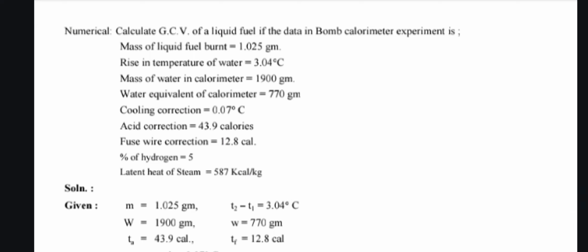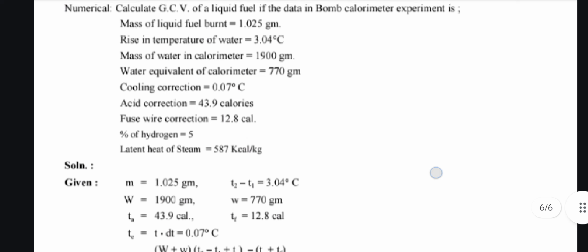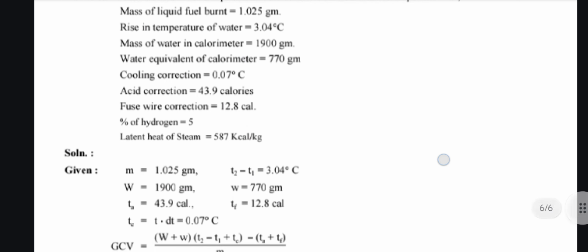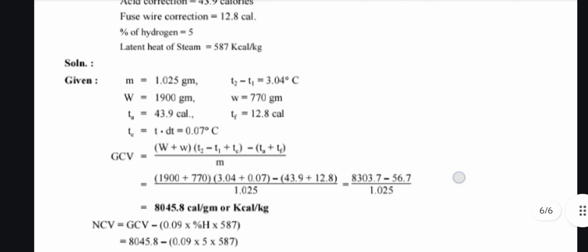This is a numerical for the bomb calorimeter. Numerical question: calculate the GCV of a liquid fuel if the data in a bomb calorimeter experiment is: mass of liquid fuel burnt equals 1.025 gram. Rise in the temperature of water 3.04 degrees Celsius. Mass of water in calorimeter equals 1900 gram. Water equivalent of calorimeter equals 770 gram. Cooling correction equals 0.07 degrees Celsius. Acid correction equals 43.9 calories. Fuse wire correction equals 12.8 calories. Percentage of hydrogen equals 5. Latent heat of steam equals 587 kilocalorie per kilogram. Solution of this one.